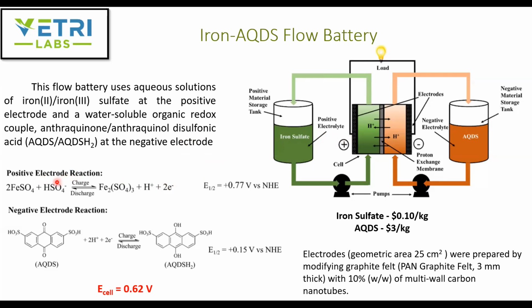If you consider the positive electrode reaction here, Fe2+ gets converted into Fe3+, with a half cell potential of about 0.77 volts. In the negative electrode reaction, you have AQDS getting reduced to AQDSH2, from quinone to hydroquinone, and the half cell potential is about 0.15 volts. So the overall cell potential is cathode minus anode, which would be 0.62 volts. For their working electrodes, they used a geometrical surface area of 25 square centimeters of graphite felt electrode, but they modified it by mixing it with 10% multi-wall carbon nanotubes to increase the electrical conductivity and also increase the surface area.